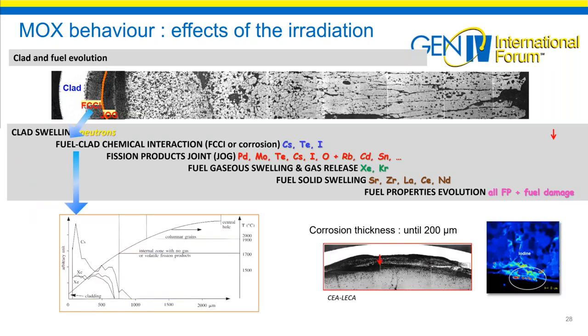The clad is also affected by a chemical interaction with the fuel named FCCI or corrosion, which leads to reduce the thickness of the tube. The interaction is mainly, as we have seen, with tellurium, cesium, and iodine. It depends clearly on the initial O/M of the fuel that has to be high for the thermal properties, but not so high for these corrosion issues. So that's the reason why the target value for the fabrication is 1.97 to 1.98 and not the stoichiometry.